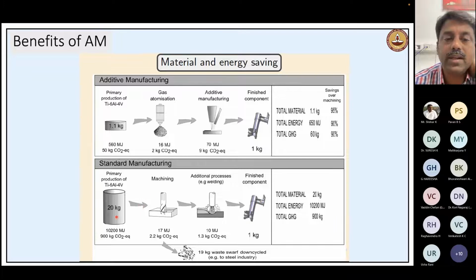To produce such a component, first we need to start from a huge billet, 20 kg of titanium, and titanium production is an extremely energy consuming process. So we end up producing a large amount of carbon dioxide, which is a greenhouse gas, isn't it, during the production of such a massive amount of titanium. For 20 kg, 900 kg of CO2 is released, and we spend about 10,000 megajoules of energy, and then subsequently we have to machine the part and weld it to produce a component. The remaining material is wasted as scrap, which has to be recycled again, and that also consumes more material and energy.